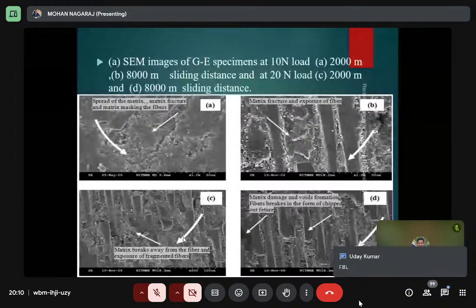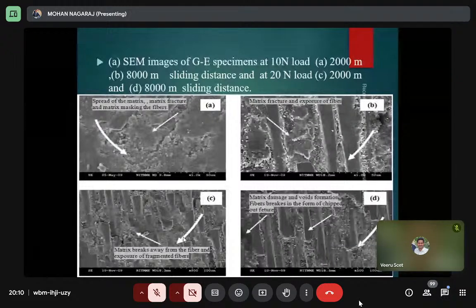D shows matrix damage, void formation, fiber break in the form of chipped features. Some images of the Jatropha filled and some of the general composite. The Jatropha oil cake filled composite has very good wear resistance because of its oiliness and also some of the presence of the oil in these materials. It covers the present pavement materials, envelops the materials, it reduces the wear, it improves the wear resistance.